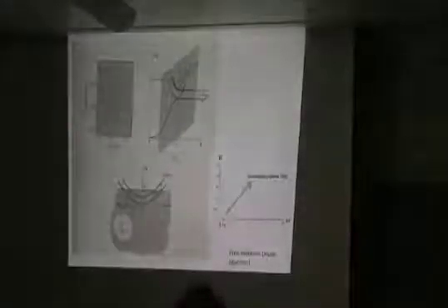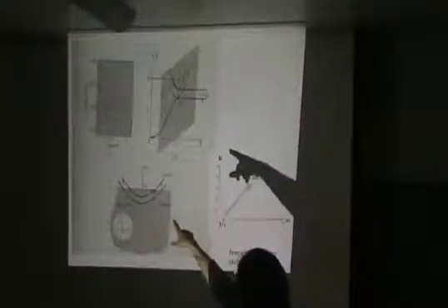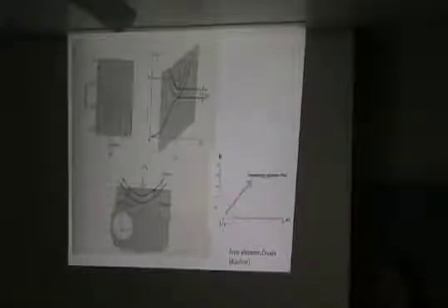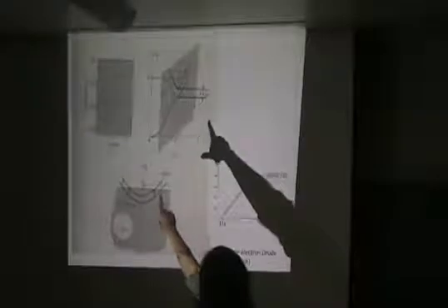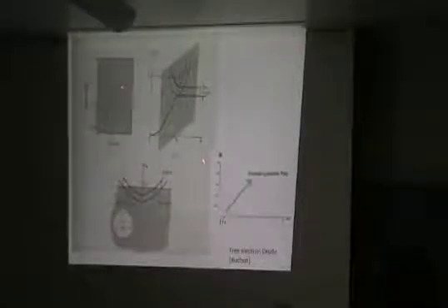Okay, now let's look at something like this. This is good old aluminum. If you look at aluminum and its reflectivity, remember 2.5 eV was yellow. What you see is its reflectivity is coming down from 1, and when you hit an energy scale which is, okay, here I have plotted Eric's results for the reflectivity of a free electron gas. And what you see is it comes down from 1, then there's a plateau, and then there's another thing. It's all very featureless. Okay?